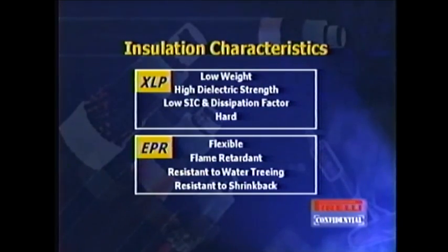EPR is also inherently resistant to water treeing, making it ideal for submarine applications and any applications where you have extremely wet environments. And that's not to say that you can take an EPR insulation system and have no strand filling and no water-swellable powder. The more you block water out of it, the less chance you have of any problem, because any insulating material, when subjected to water and voltage stress, will tend to degrade. But EPR is inherently much better than the cross-linked polyethylene materials.